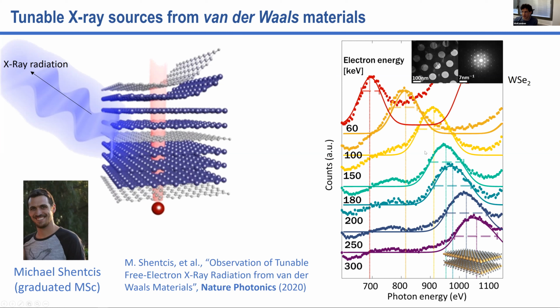And this is an example of the EDS measurement, where we look at the radiation emission as a function of the electron energy. And we see that by changing the electron energy in the microscope from 60 kilovolts to 300 kilovolts, we actually change the location of the X-ray resonance. What we get here is a tunable source of radiation that can be created with van der Waals materials. And we also find that the actual composition of the van der Waals material, this is the example for WSe2, but we did that for 6 different van der Waals materials, is giving us precise control over the behaviors of those peaks, the angular spectrum of the X-rays, and also the spectrum of the color of the X-ray.